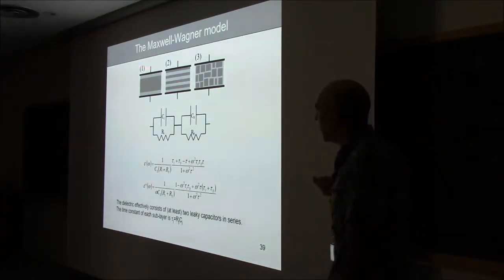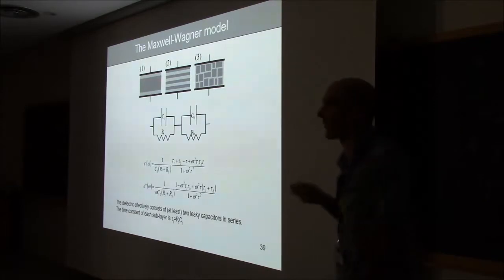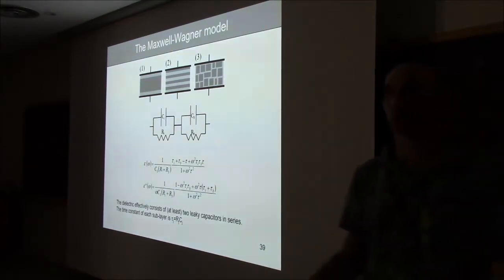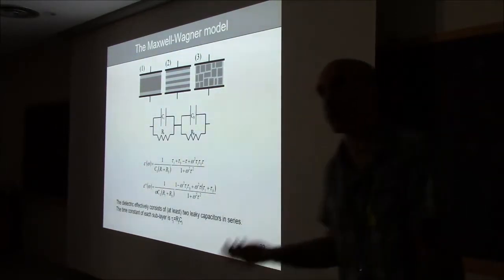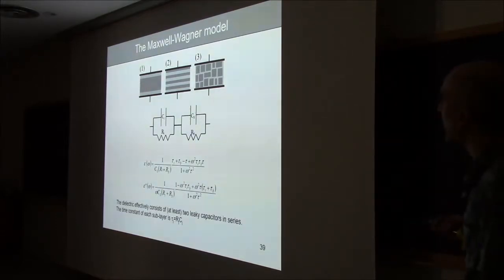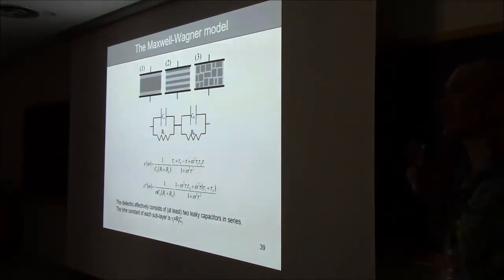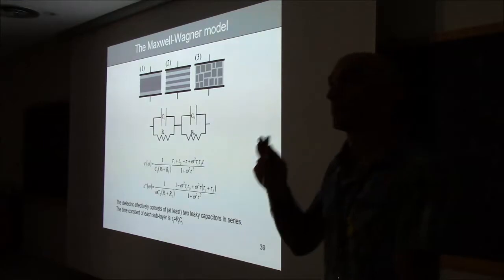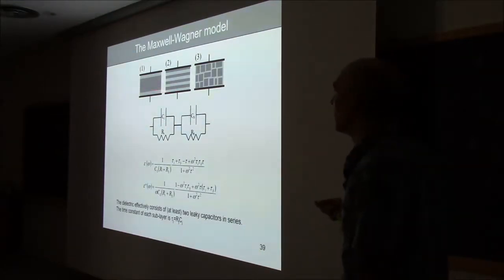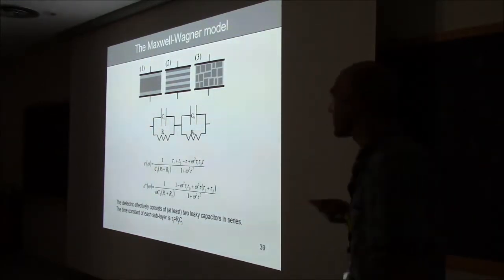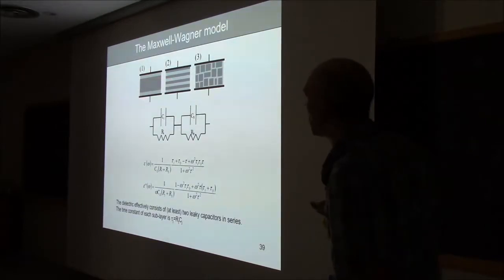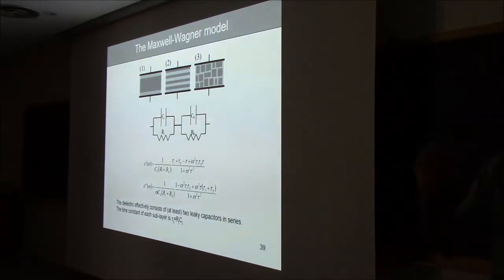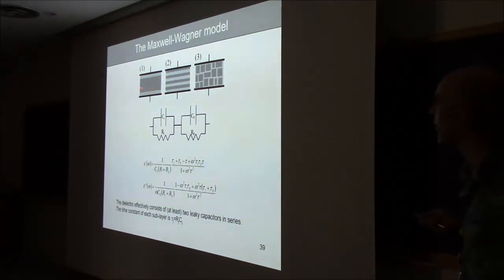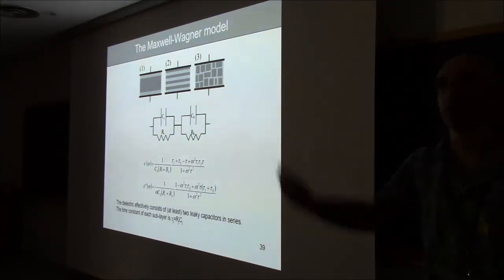Imagine that your dielectric material is not a perfect dielectric, it's a semiconductor, and we know that all dielectrics are ultimately a bit semiconducting. They have finite band gaps. Point 1. Point 2, imagine that your material is not homogeneous. So basically you have two components, maybe the interfacial component and a bulk-like component, or you have something that is mixed in some way. So you have some areas that are more conductive than others.